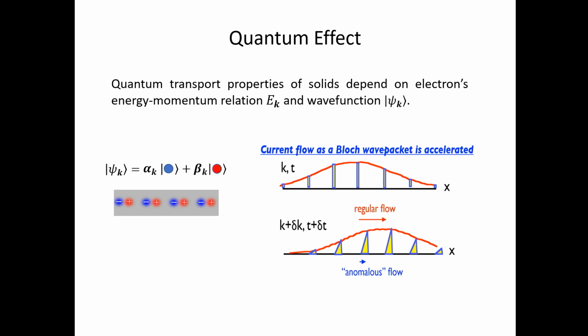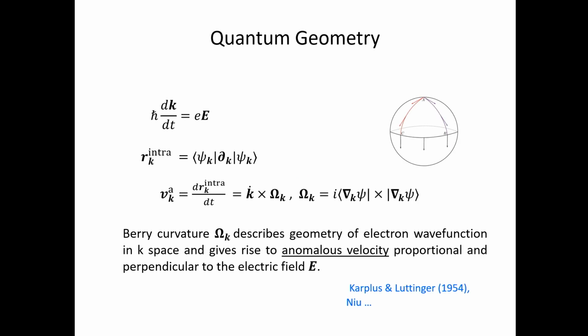So in the presence of an external electric field, the center of mass momentum is accelerating. This is basically the quantum version of just Newton's law. However, as crystal momentum changes, the distribution of the electron wave packet within these two types of atoms is also changing. So you can imagine that as K increases, more and more weight of the electron wave function in the unit cell is on the red atom. So this then creates an additional current, the so-called anomalous current. This is an unusual effect, where the electric field actually generates a current instead of generating acceleration.